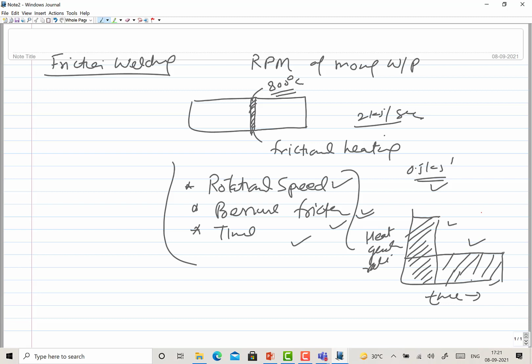The short time is beneficial because you are achieving the desired temperature at the interface in a very short time. So heat dissipation to the underlying base metal is very limited, and therefore you get the narrow heat affected zone. On the other hand, when you are working with the low heat generation rate, then you take longer time to achieve the desired temperature, and in the meantime a lot of heat will be dissipated to the underlying base metal, and that will be leading to the wider HAZ. Okay, so it is important at what rate you generate the heat, and that significantly depends on these two things only, because time is another kind of factor, because we are talking about the rate of heat generation.